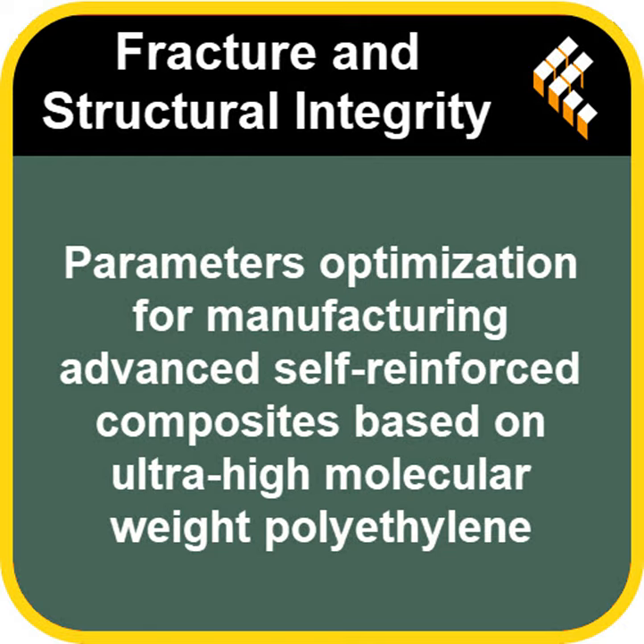I think it really comes down to that intricate balance, that constant interplay between competing effects during manufacturing. The double-edged sword again. Exactly. You increase the temperature, and yes, you enhance that crucial interfacial bonding through molecular entanglement, that's good. But push it just a bit too far, and you simultaneously start reducing the amount of that highly oriented fiber core, your main reinforcement, that's bad. And that creates this very narrow window. A really narrow optimized processing window that you absolutely have to hit to unlock the peak performance.